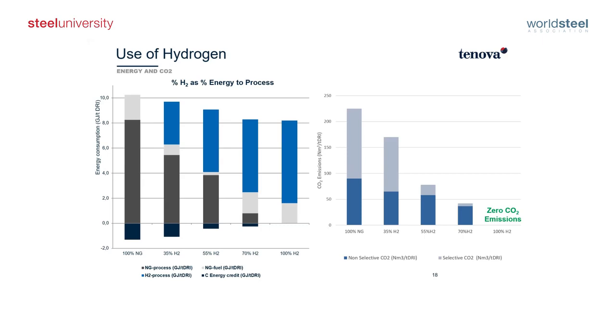So even this quota, this blue quota, can be dramatically reduced or brought down to zero simply by eliminating the use of fossil fuels for reheating the gas. There are experiences now ongoing with electric heating, for instance, that would zero entirely the CO2 emission independently from the content of carbon inside the module.